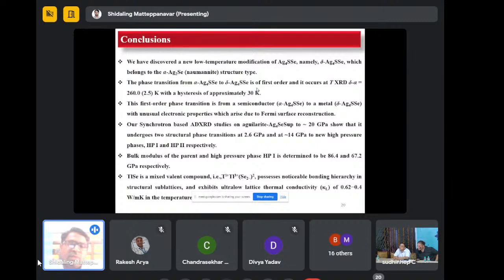And this is my conclusion. Overall, I can say that in the Ag8SSe sample, there is no charge density wave and superconductivity. The only thing is that the structural transition is happening with the Fermi surface reconstruction. Because of that reason, we are getting such a low resistivity. And TlSe is a very good low thermal conducting material.